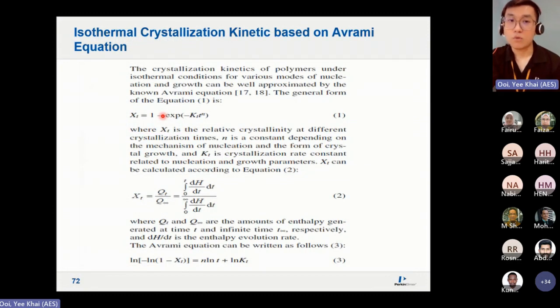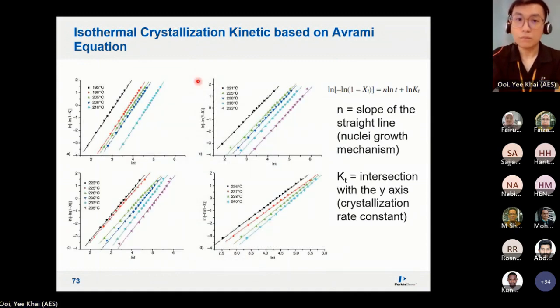With DSC, we can also do isothermal crystallization kinetics. As mentioned just now, we are based on a multiple curves method. For kinetics, at least 3 curves, maximum 6 curves, in this case at different isothermal temperatures, since I'm holding it at different temperatures. They want to know the crystallization kinetics for the crude oil. So with 6 curves, what we want to get is the n and also the kt from the intersections.